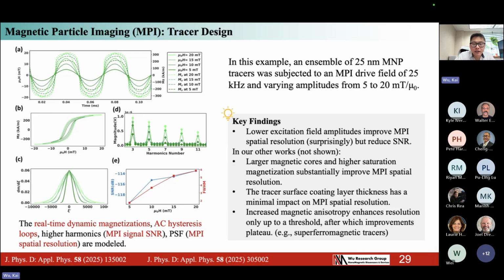This slide shows you some data we collected by modeling the dynamics of nanoparticles under the AC magnetic field in MPI applications. So this will guide us in the nanoparticle tracer design. As you can see, in the time domain, the response of nanoparticles always has a phase delay to the AC magnetic field you apply. This is because the Brownian and Néel processes will cause a delay of the response of particles to the AC magnetic field. We can also reproduce the AC magnetization loop of the particles under this AC field based on the time domain magnetization curve, the MT curve, as well as the higher harmonics of particles under one frequency AC magnetic field, 3F, 5F, 7F. All these harmonics will be used for the image reconstruction for MPI imaging, as well as the signal to noise ratio and also the point spread function, which is related to the spatial resolution of MPI imaging.